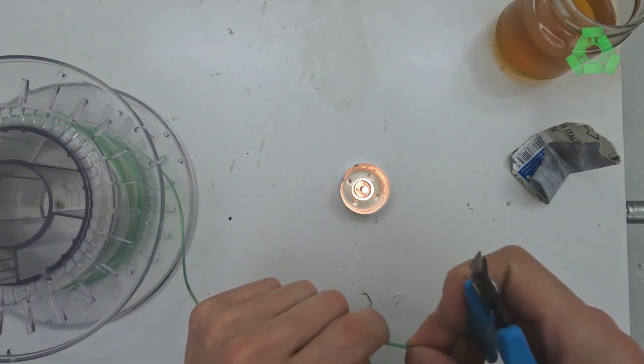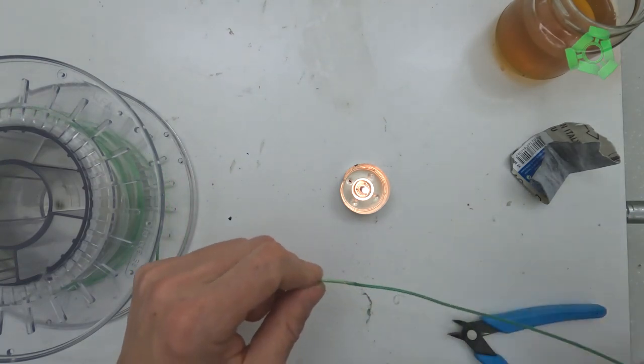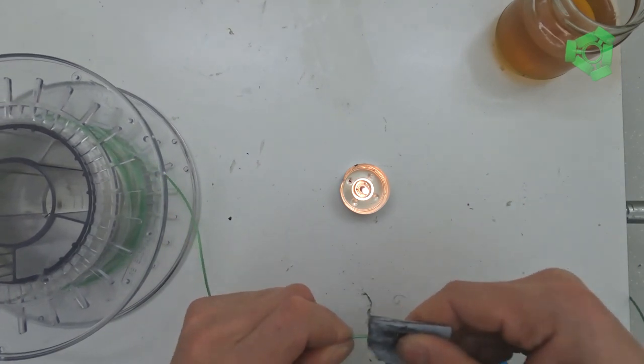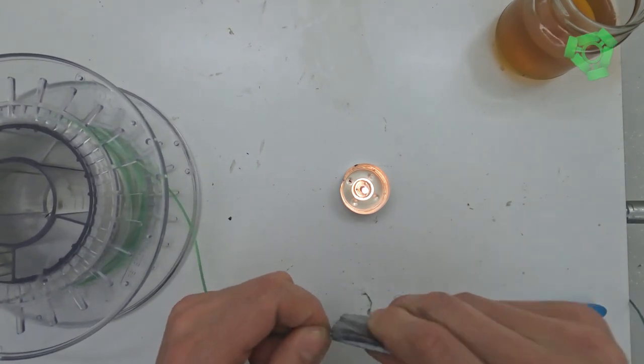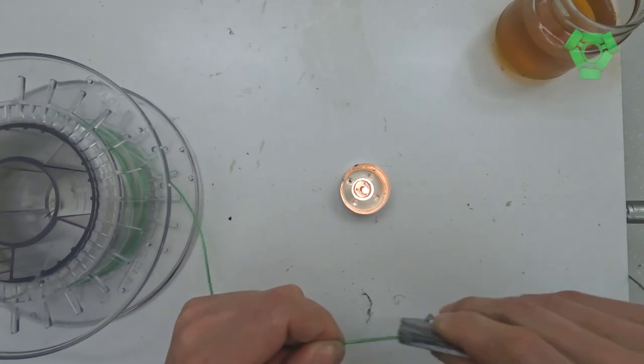And sand with 100 to 260 grit sandpaper if necessary. The transition between the two sections of filament has to be perfectly consistent in order for it to pass through the 3D printer's filament feeder. Slightly too thick and it will jam the machine, while slightly too thin and the feeder will not be able to put enough tension on it to feed it into the hot end.